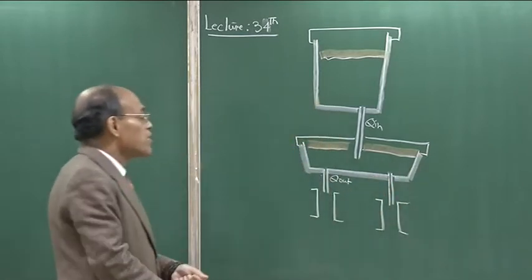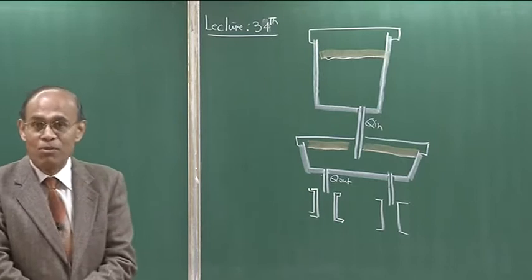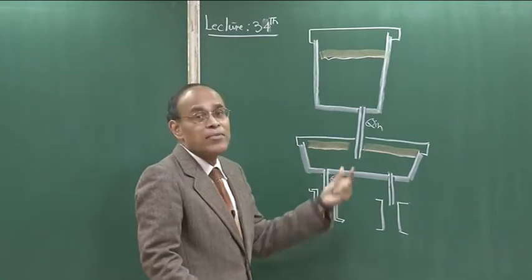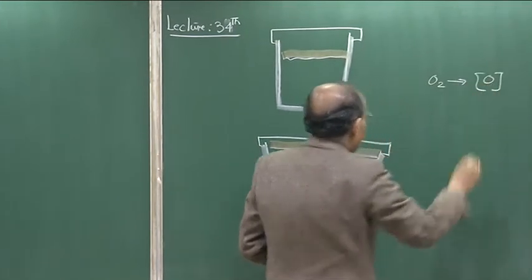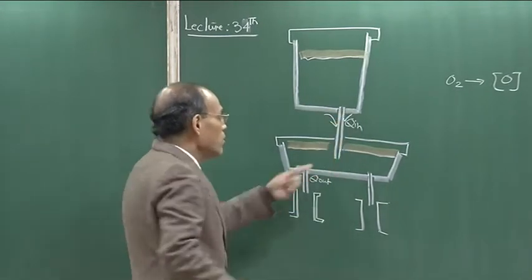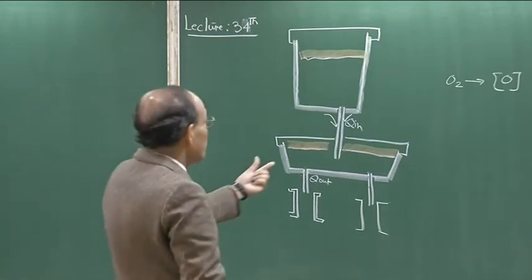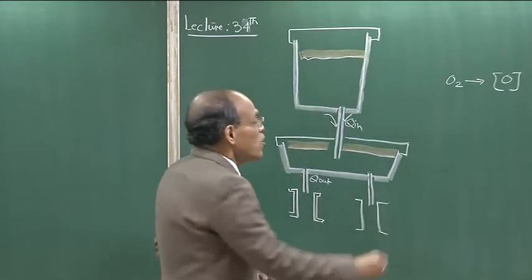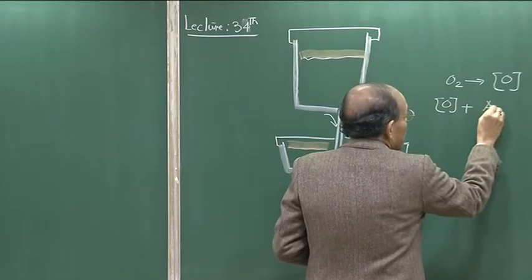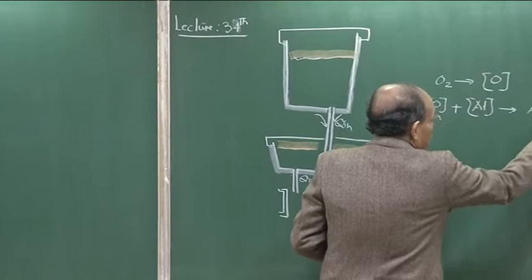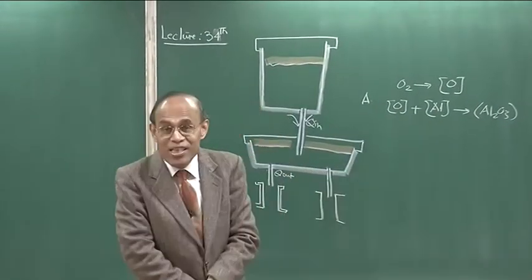The key point is that in the tundish there is considerable scope for reoxidation of steel. Reoxidation is primarily the major chemical reaction that takes place in the tundish. The first mechanism is dissolution of oxygen from the atmosphere — due to ingression of air, or during the initial period of tundish filling if the tundish is not flushed — leading to oxygen dissolution in molten metal. This disturbs the aluminum-oxygen equilibrium, generating alumina inclusions.